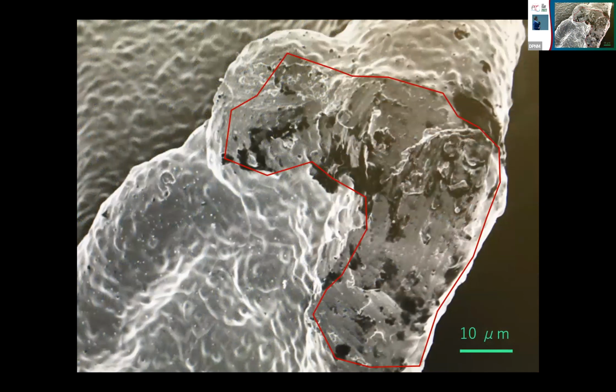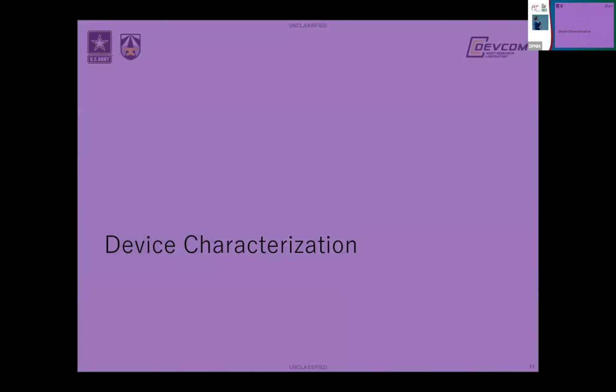Now, I spent about a year with nothing but shorted foams, which was incredibly fun and frustrating. And these substrates are really hard to do subsequent metrology on because there isn't a flat surface to be found. There's very low density. And it wasn't until some careful SEM inspection that I found something that looked like this. And as I mentioned in an earlier session, my thesis was on tribology, so a sliding wear track is something that I'm familiar with seeing. And as soon as I realized that flexion was okay, but sliding absolutely destroyed our ALD coating, I was able to start testing these foams. So let's move on to some device characterization.